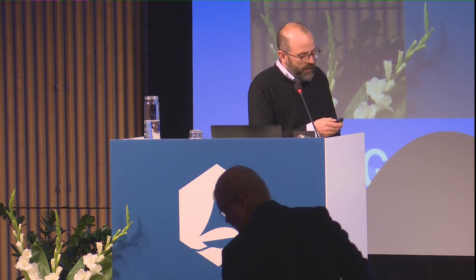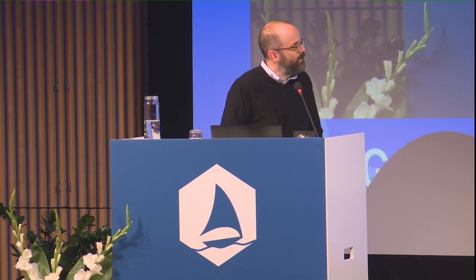Okay, so that's interesting. Most recently, this is work that's not published, but it's coming online, I think, in about a week or two. What we've thought about is if we have a similar system, we have graphene, we can put boron nitride on top. We also have boron nitride on bottom. In the previous measurements, we were assuming that this bottom BN was just at some large but unknown angle relative to the graphene. Now what we want to do is think about controlling all three of these angles. So we'll call theta bottom the angle between the graphene and the bottom BN, and we'll call theta top the angle between the top BN and the graphene.